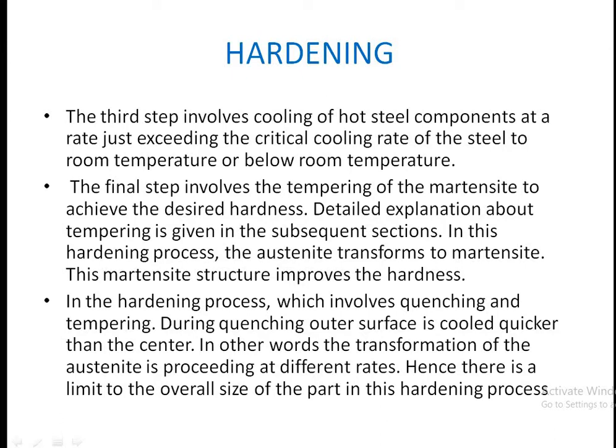Understanding the hardening process helps clarify what case hardening means. During quenching, the outer surface cools quicker — when you immerse a heated part in water, the outer surface gets cooled first and then the inner part cools progressively. In other words, the transformation of austenite proceeds at different rates, and hence there is a limit to the overall size of the part in this hardening process.